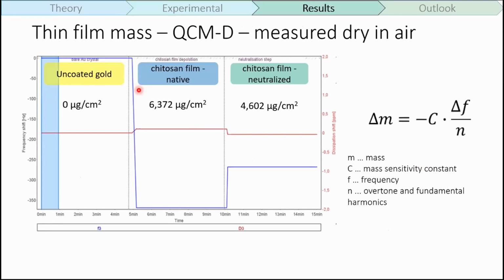With that in mind, we then measured the mass of the film coated on our QCM crystal. To start, we did a baseline measurement of an empty crystal where the frequency is 0. Then after chitosan film was deposited, the frequency shifted to -360 Hertz, which corresponds to 6.3 micrograms per square centimeter, calculated using the Sauerbrey equation.